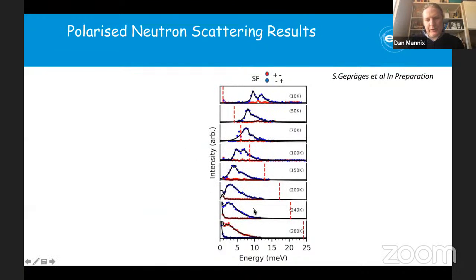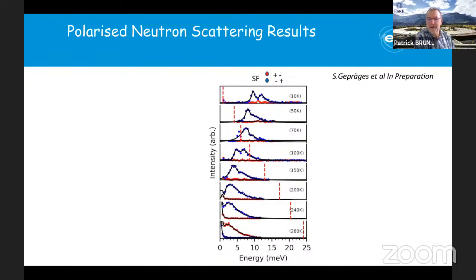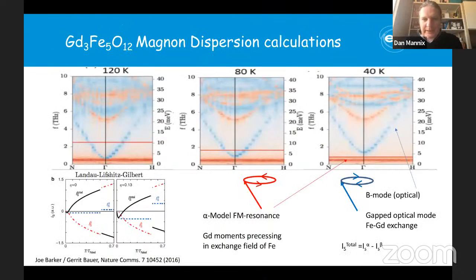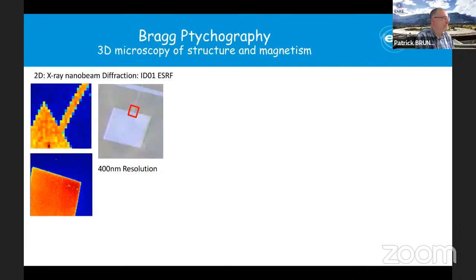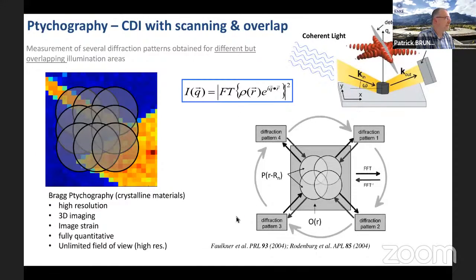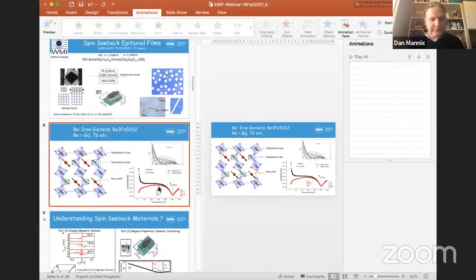If we go to the compensation temperature, we only have data above and below, not right at the temperature. So Tim comments, yes, I understand, but the black curve was just the gadolinium moment? In the magnetization data? I guess so. It might take me a while to go back, so I can just go back to this. Okay, so here we have, I think, field cooled and zero field cooled. Now this is the total, it's SQUID data, so this is basically measuring the magnetic response outside. Oh, it's a macroscopic magnetization, not the gadolinium. Yeah. Okay. Measured outside the sample.